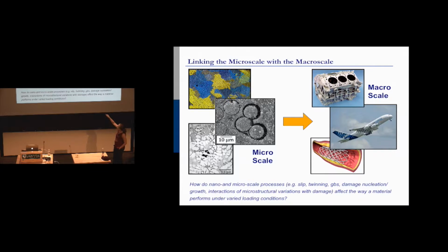The way that you do it is you have this SiC matrix, and then you have a SiC fiber, and you put a weak boron nitride coating on it. And so now you've got to dissipate energy somehow, right? But you want the ceramic because it's high temperature. So now when a crack comes along, it hits the fiber, and it's either going to deflect up, or it's going to deflect around, and that dissipates energy. So you have many, many, many of these fibers, and you're constantly dissipating energy by the deflection of cracks. So cracking is not bad.